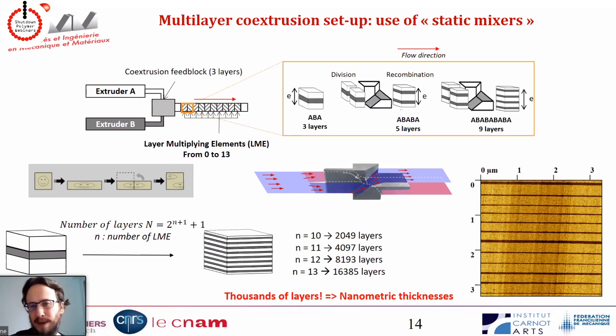So if I do that with 10 multiplying elements, at the end, my film will have, say, 2,000 layers. And because its total thickness is 100 micron, each layer will be something about 100 nanometer or less. If you look at that on the AFM, so I look at it in the thickness direction, you have all these layers, all this millefeuille structure. And you can see that in black or in brown, the layers are maybe 100 nanometer, and the yellow ones are another polymer and are a bit thicker, so maybe 500 nanometers.